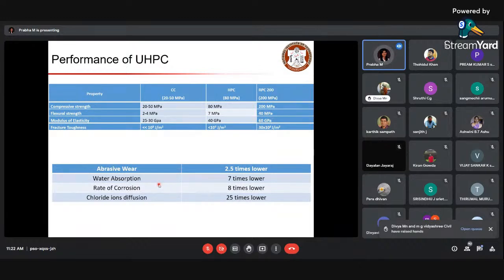When we check the application of this high performance concrete, abrasive wear is important because it has very good strength and toughness. So the abrasive wear will be about 2.5 times lower than your conventional concrete. And water absorption, because these are finer materials, the pores will be very less and you have a denser matrix, so the water absorption will be 7 times lower, rate of corrosion will be 8 times lower, and chloride ion diffusion will be about 25 times lower than your conventional concrete.